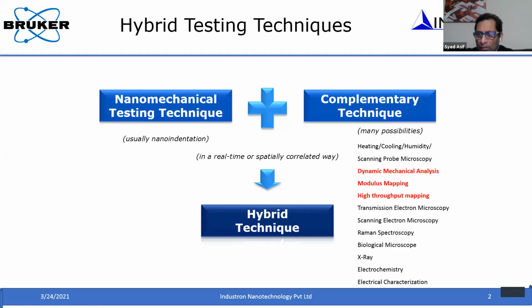So I think by now most of you are probably already familiar with what a nanoindentation technique is. And here what I'm trying to do is show what you can combine with this nanoindentation technique, which we call a kind of hybrid technique, and then make use of the full suite of the instrument. So nanoindentation is basically a depth sensing technique where you apply a load and measure the penetration of the indenter tip into the sample as a function of load. And then, like Prita presented, you measure the stiffness from the unloading curve and calculate the hardness and modulus of the material through the Oliver and Pharr method. That is the straightforward nanoindentation technique.